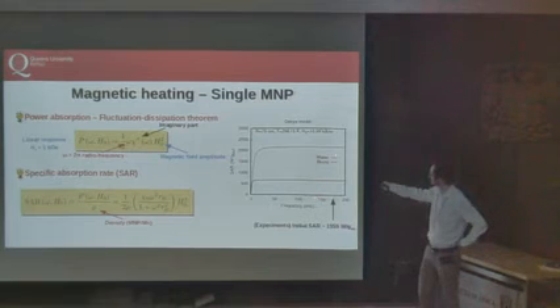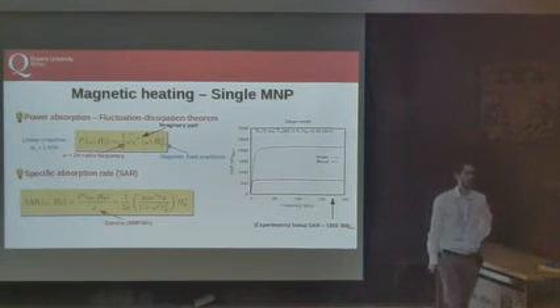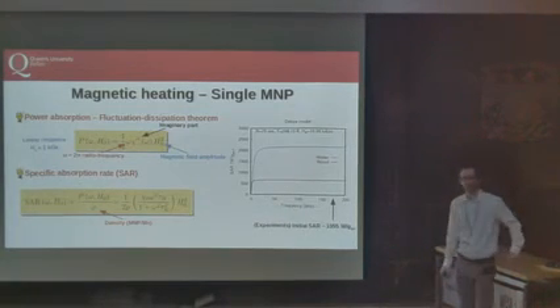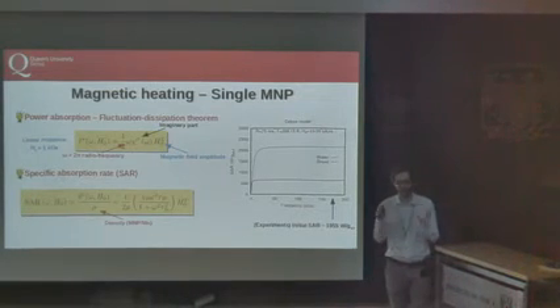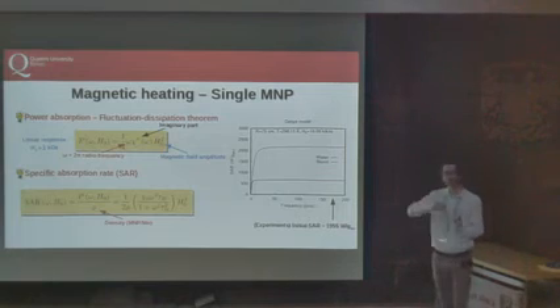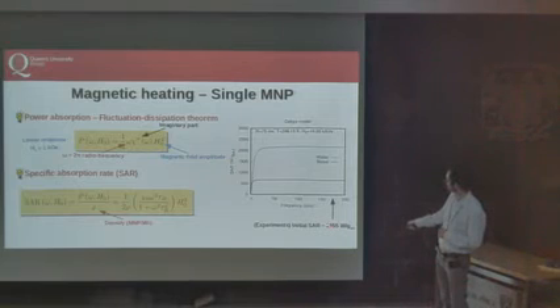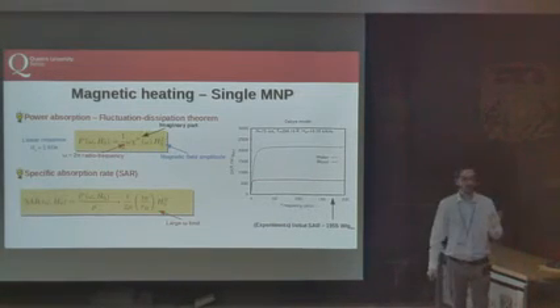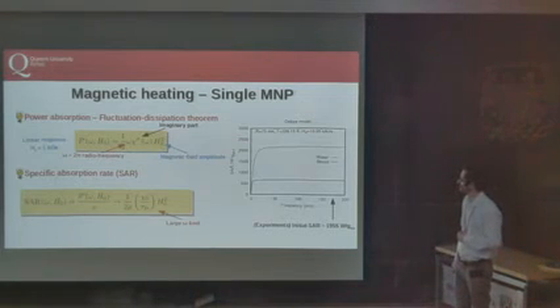And by the way, our value here is not very far from what is measured in experiments. This is just an interesting result. It's difficult to claim we are spot on. There are too many variables, but it's not miles away. The initial slope in the experiment is 1955. This is in excess of 2000. And if we operate in the limit of large frequencies, this is independent of the frequency.